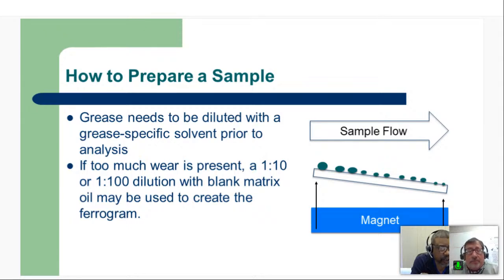How big is it and what's there? Yeah, and you just got to remember what your dilution factor is when you start comparing results to each other over a period of time. Okay, so that's the big key there. We see that in practice by taking a little marker and writing right on the slide cover, the ferrography holder, if you will, what that dilution is. So that becomes at the forefront of the analyst's interpretation of what they see. And when you say, hey, there's a lot of this or a lot of that, there also needs to be this kind of qualitative assessment that factors in what that dilution really is, especially if we're following up a previous sample from the same equipment, and now we're into a dilution situation.